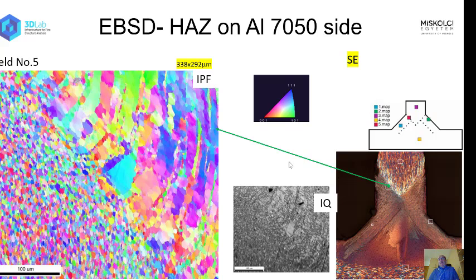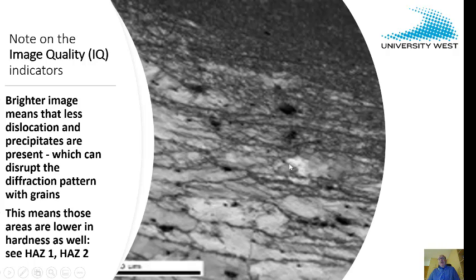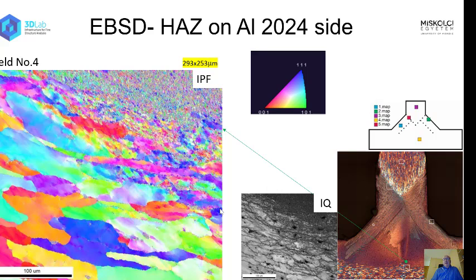So this is really the key for going forward. We thought that using this image quality indicator is a very good way to detect whether we have dislocations and precipitates within the coarse grain heat affected zone, because they interfere with the diffraction pattern. And so we concluded, by golly, these are all solutionized, let's do heat treatment. And this is really our meek contribution to the project, that we recommended, based on this analysis, that we do this light artificial aging process, and lo and behold, it worked.